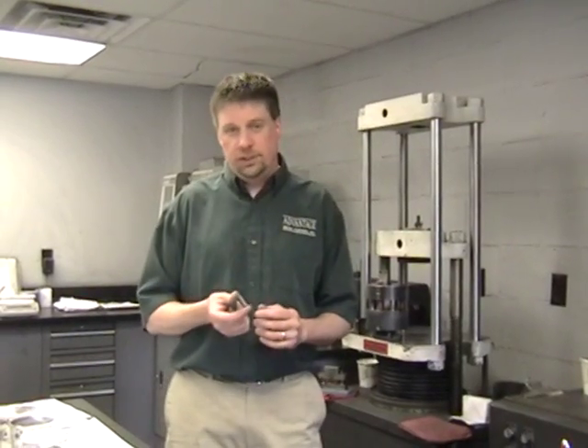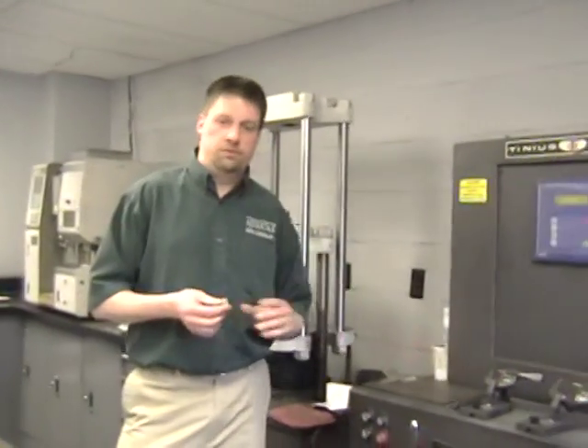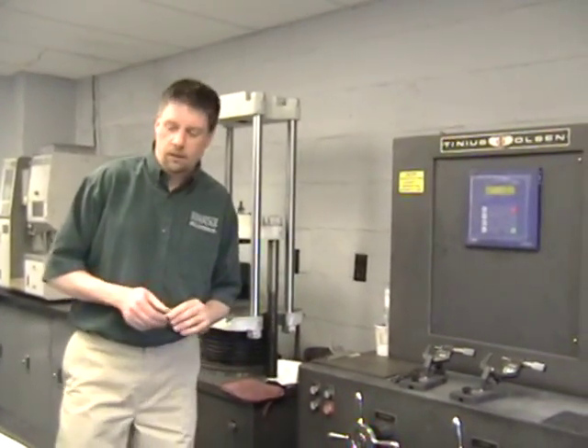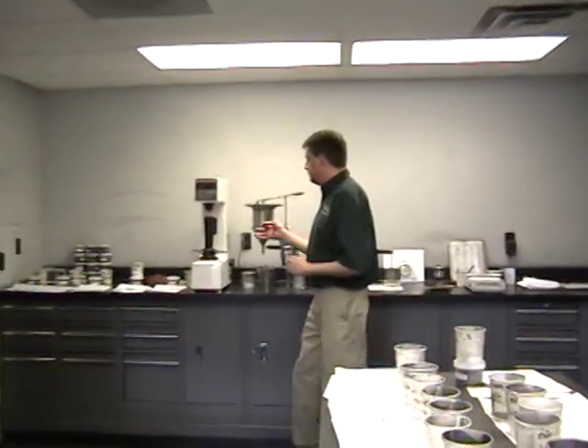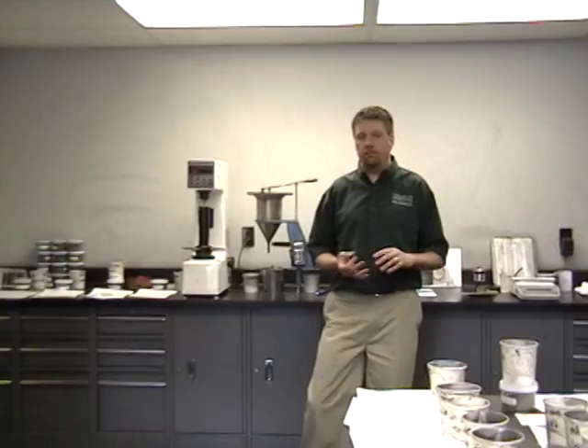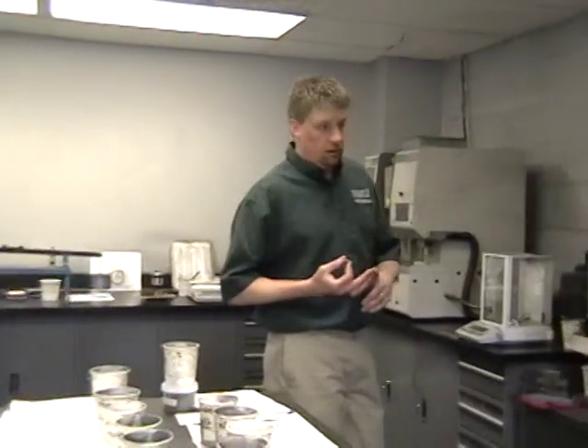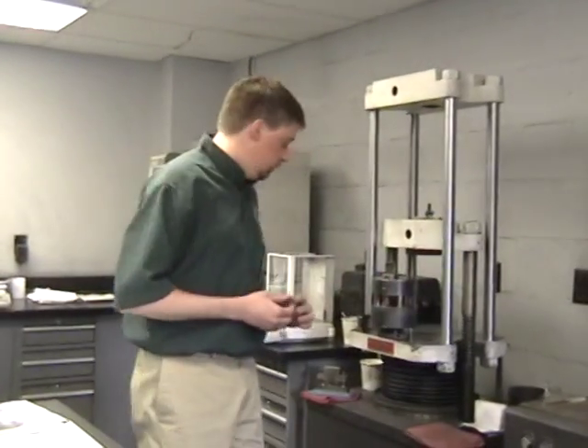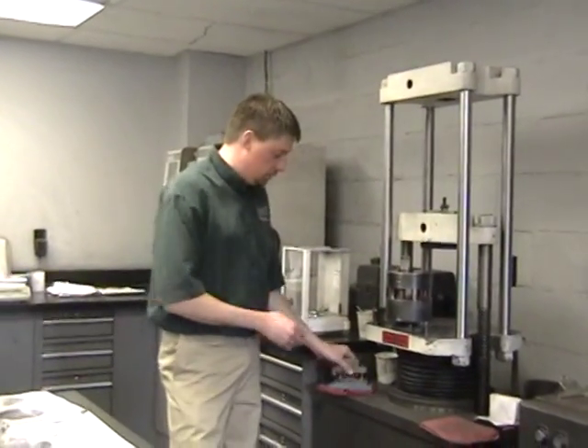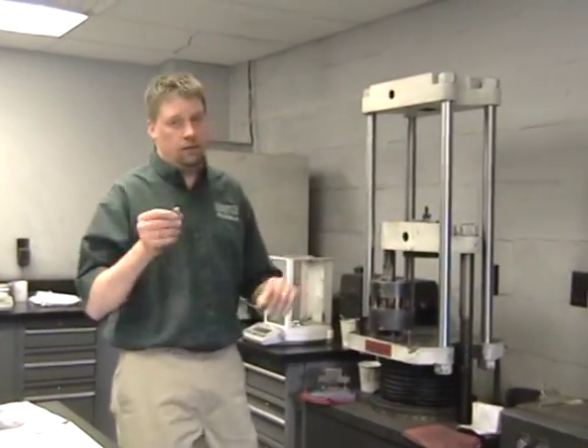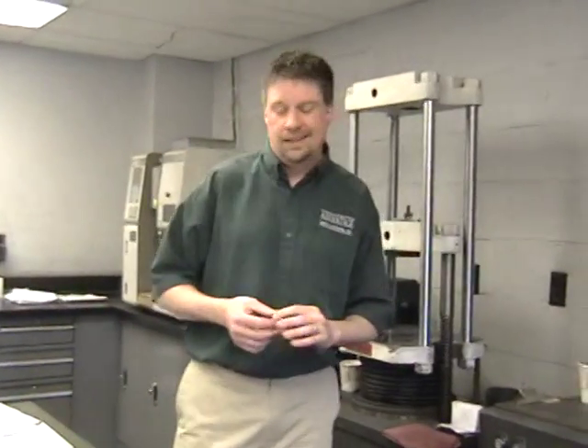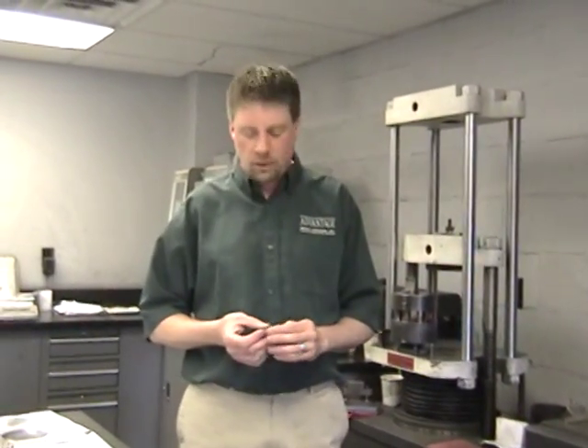After those bars are sintered, they bring the bars back in here. They measure the bars for dimensional change. They then take the bars and check them with the hardness tester for, depending on the composition of the mix, HRF, HRB, or HRC scale. After checking the hardness, they take the bars and put them into our transverse rupture fixture and break the bars with our Tinius Olsen. That gives us our transverse rupture.